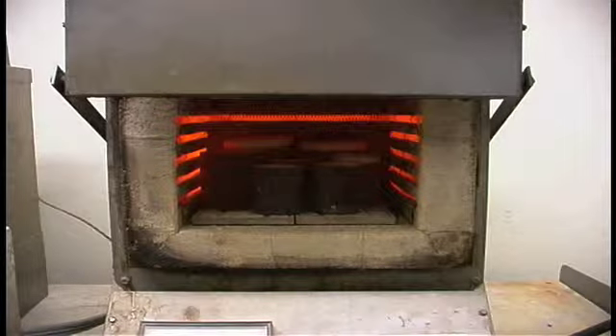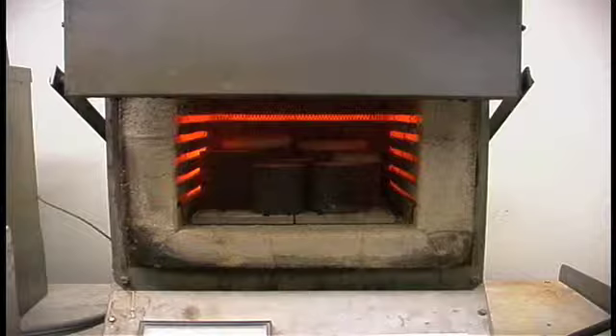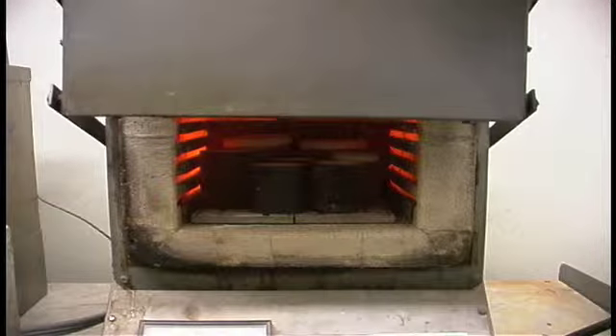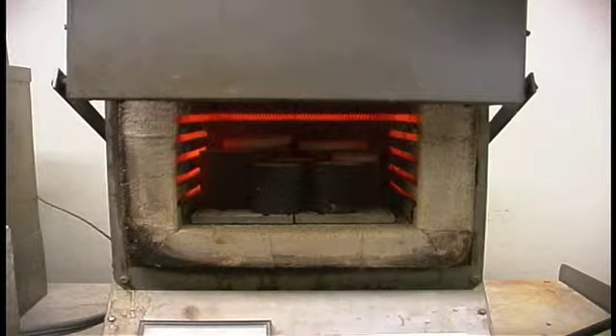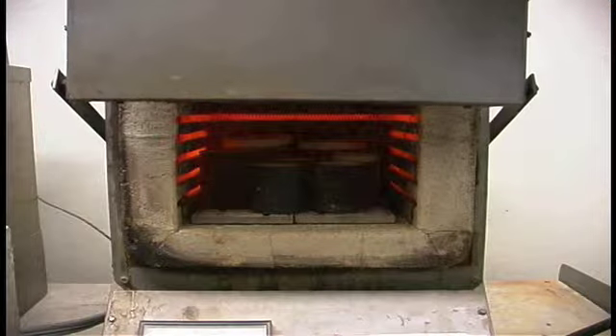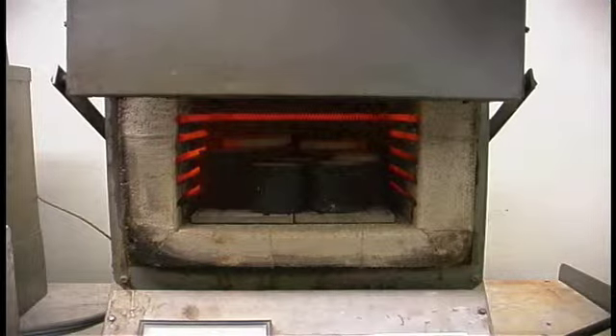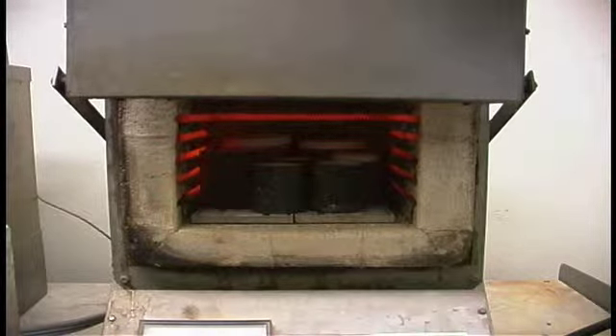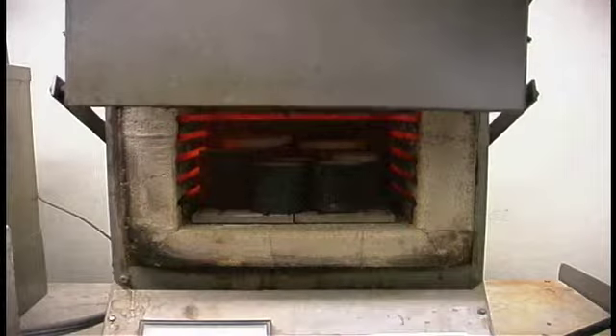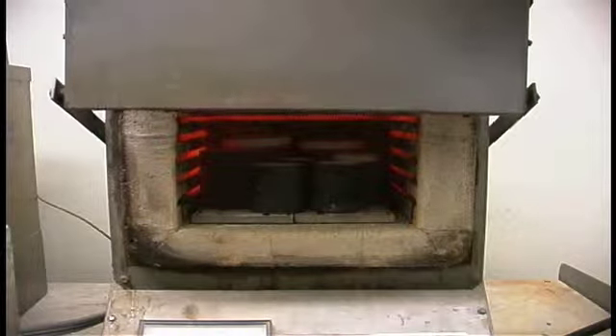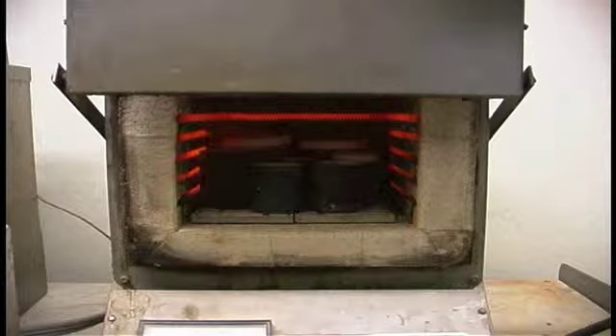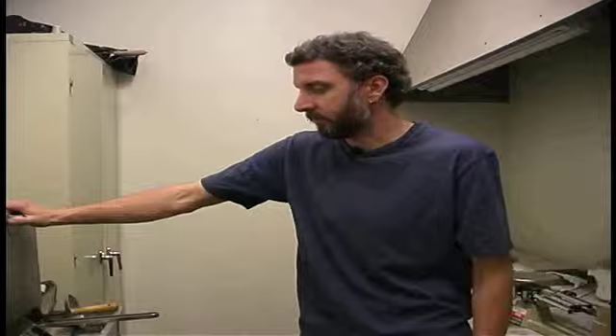Generally, depending on how many molds we have in here, we heat our kiln up to 700 degrees Fahrenheit for 2 hours. And then we bump that up to 900 degrees for another 2 hours. And then we bump that up again to 1200 degrees, and we maintain that 1200 degrees until we're ready to cast. So it's about a 6 to 8 hour process for our burnout. We call that a burnout when we're actually burning our wax material out of our molds.